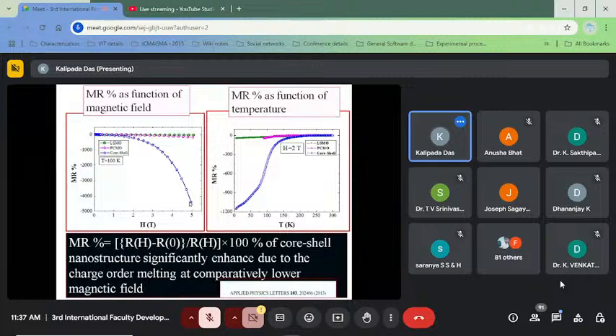And the main result is given here. Magnetoresistance as a function of magnetic field at a particular temperature, say 100 Kelvin, we have measured. And we see that in the case of LSMO or PCMO, in both cases the magnetoresistance is very low. However, in the case of the core-shell sample, the magnetoresistance is enhanced manifold. Similarly, the temperature dependence also showed the same phenomenon. That is, in LSMO and PCMO, the parent compounds, it is very low, but the magnetoresistance is enhanced manifold in the core-shell type sample.